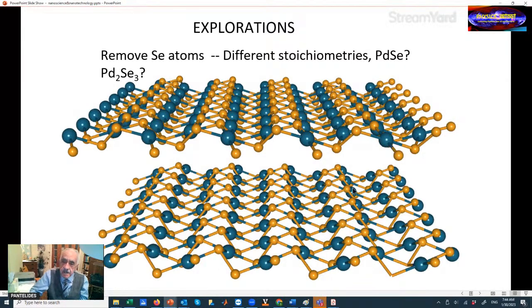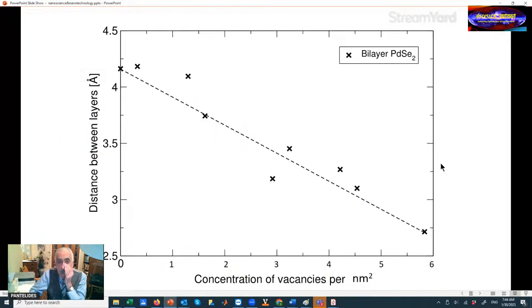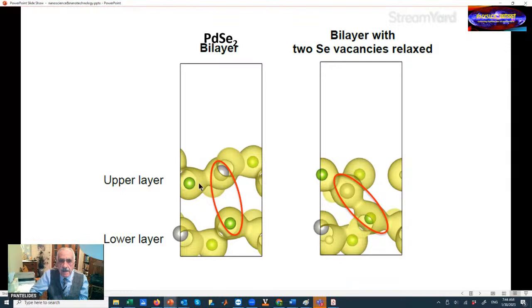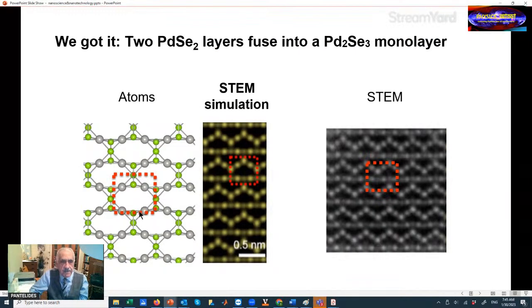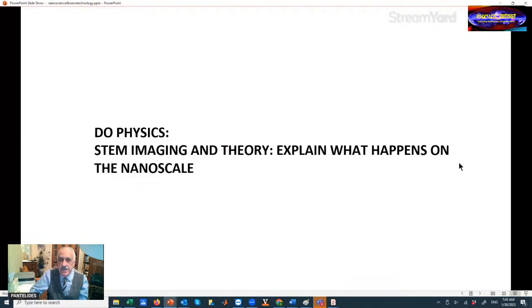We tried a bilayer and studied the possibility of how the 2 bilayers might join together to form a new monolayer. And we demonstrated that by removing seleniums, the distance between the layers decreases more and more. And when they decrease enough, the upper layer and the lower layer, the electron distribution, which is in this yellow color, when they get very close, when you have a lot of selenium vacancies, they form bonds between them, and they lead to a new structure. We identified the structure, we did the STEM simulation, and it matched this. So we did more things with this material, but it shows you how you can generate a new material.